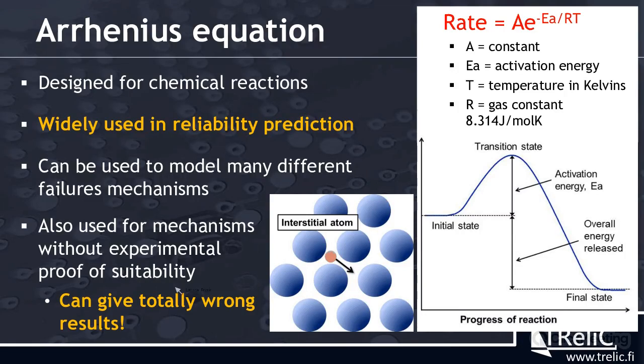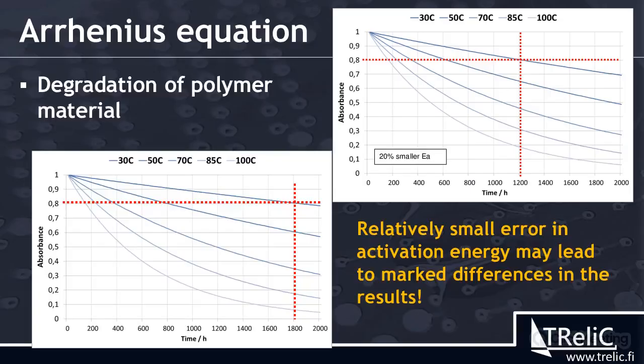But as I said, it's actually quite common that you can see Arrhenius used for complex structures. And this is very risky, and it can give totally wrong results, because you need to be sure that the failure mechanism stays the same. If you test at high temperature and then lower temperature, you need to be sure that the failure mechanism is the same. Otherwise, this is not valid anymore.